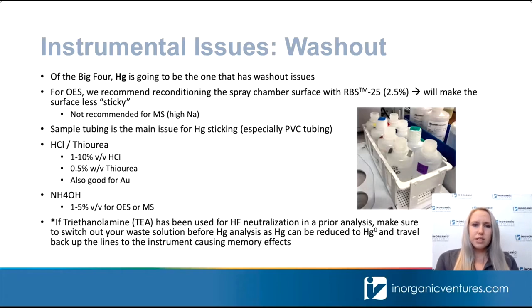For your rinse solutions, we do recommend using hydrochloric acid with thiourea added. So 1 to 10% hydrochloric acid with 0.5% weight to volume thiourea added. And just as a side note, this also works really well for washing out gold. So if you're having issues with gold washout, definitely give this a try, because we've had really good results from this. A basic solution you can use is ammonium hydroxide at 1 to 5%. And that's for both OES and mass spec.